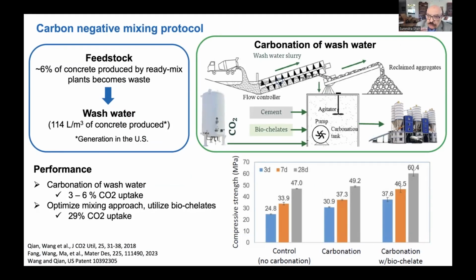We know that when we have a ready-mix concrete, when it comes back, you wash the ready-mix concrete and that produces slurry. Now, from the slurry, after you remove the aggregate, you take that slurry and inject it to CO2, then what you have is supplementary carbonated material, which leads to supplementary cementitious material. And this is indeed, we showed the compressive strength of controlled specimen and carbonation of controlled specimen, and then with carbonation with the addition of supplementary cementitious material, that is carbonated waste slurry. So you got rid of the waste slurry and also you absorb CO2 and produce supplementary cementitious material.